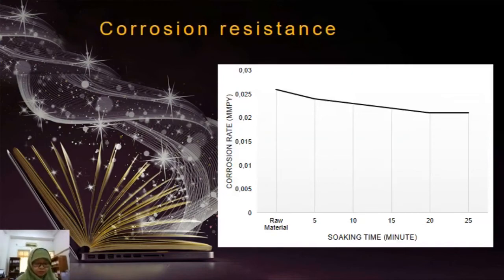The last, corrosion resistance. Corrosion testing was carried out by using the weight loss method in a 3.5% NaCl solution. Corrosion test results show that the FeCrMn alloy has a corrosion rate of 0.026 mm per year. The high corrosion rate of FeCrMn alloys is due to the possibility that the forging process has been carried out after making FeCrMn alloys in cylindrical form. The forging process causes a smaller grain size and residual stress, thermal stress, which triggers a potential difference. The greater the stress given to the material, the greater the potential difference, resulting in a greater corrosion rate.